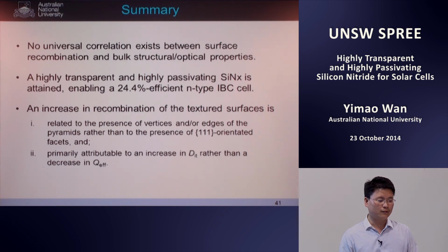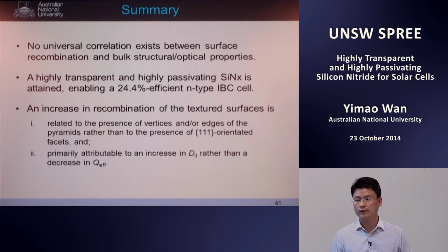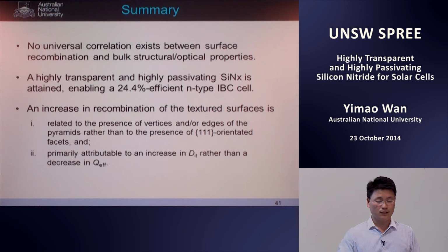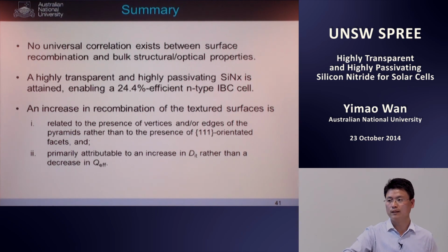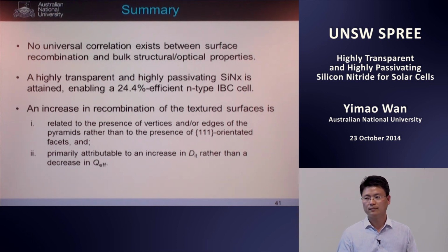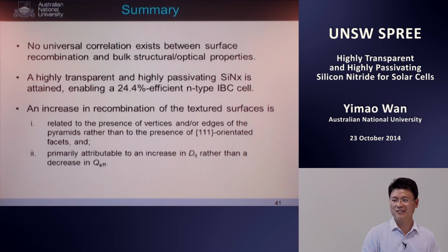One of the theories we have is that it is due to the deposition, where the film is deposited on top of the surface rather than grown by reaction with bulk silicon, which exposes the orientation in the bulk. So comparing the thermal growth and the deposition process, the exposure of 111 or 100 orientation or the dangling bonds is quite different. But I haven't seen any literature on this research. That's a good research topic.